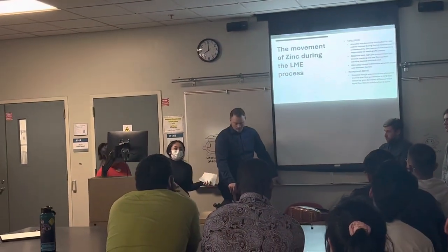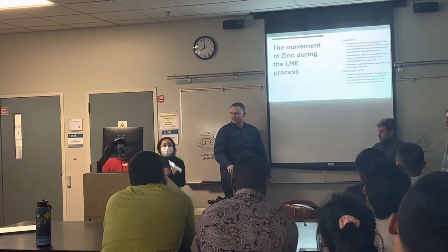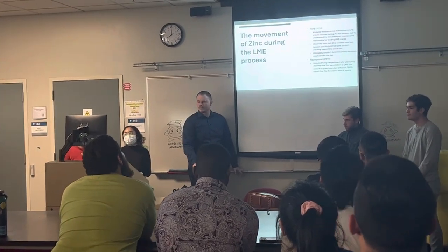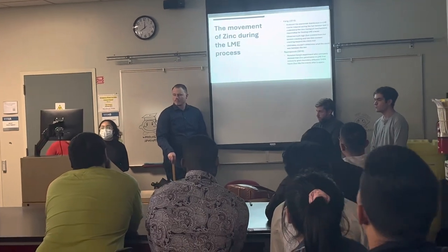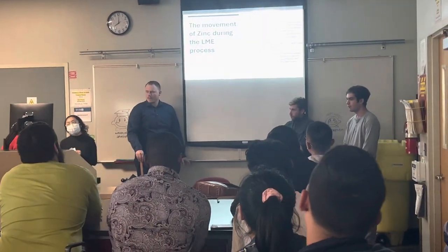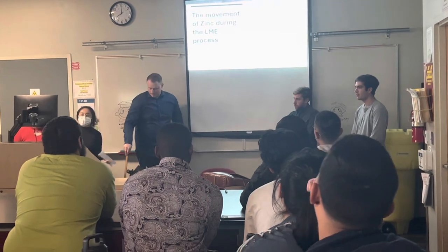So Rasmussen in 2018 conducted that same experiment again, and he ultimately showed that the zinc penetration and liquid metal embrittlement first occur by grain boundary diffusion, and then it looks like liquid zinc fills the cracks after it opens. And this is a schematic drawing of the zinc penetration.